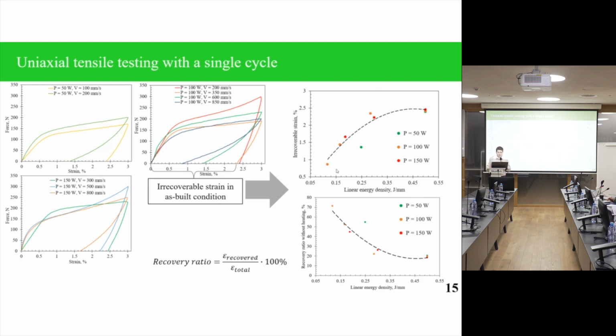Results of the second test are shown on this slide. Here we can see that samples manufactured by different combinations of process parameters result in different irrecoverable strain in the as-built condition. And if we plot this result as the dependence of irrecoverable strain on linear energy density, we observe the positive trend, and after some critical value, it comes to the saturation point.